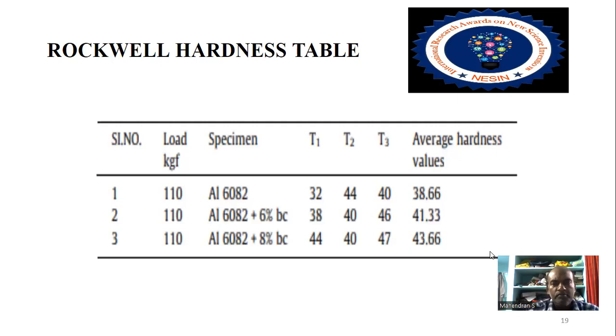These are the very good example. There is a constant load, 110 kg. This specimen, same specimen, aluminum 6082. Next one is aluminum 6082 plus 6% of boron carbide. Next one is aluminum 6082 plus 8% of boron carbide. The average hardness values are increased